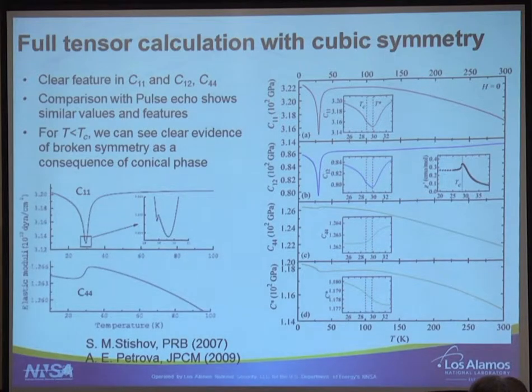The other thing that I can say is that if we look for breaking of the symmetry below Tc, we have clear evidence that we can see how the symmetry is breaking when we get into the helical phase. I don't have time to show the details, but let's say we solve this as a tetragonal system, the tetragonality is constant at higher temperatures, and then we see how it evolves as we go below Tc. So this is a very sensitive technique.